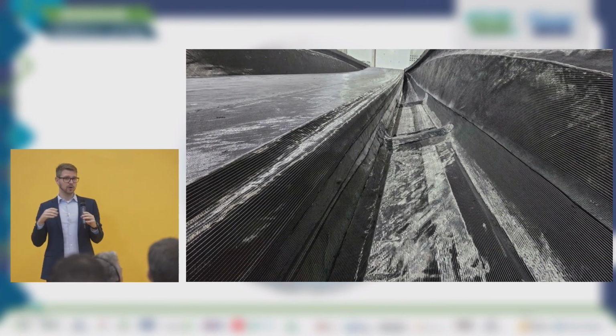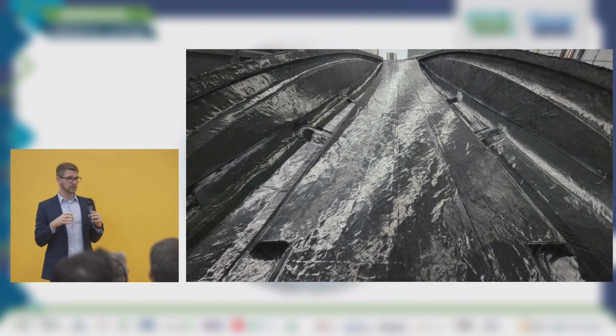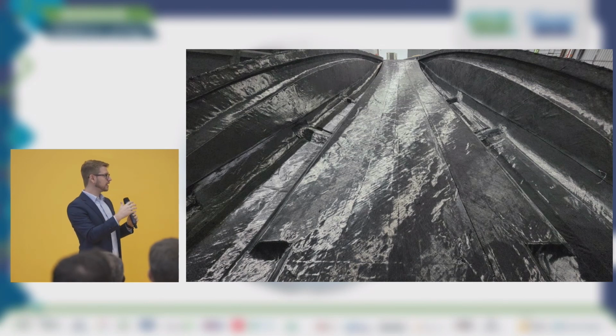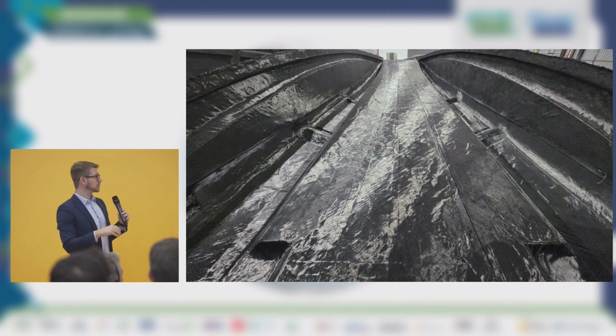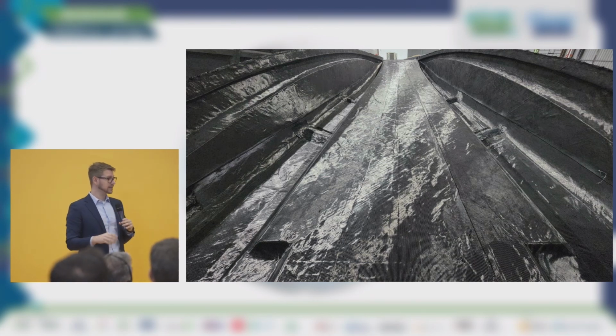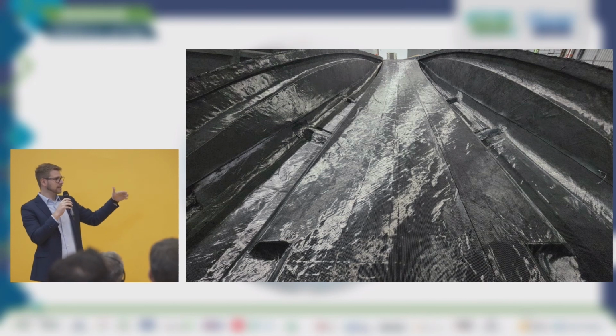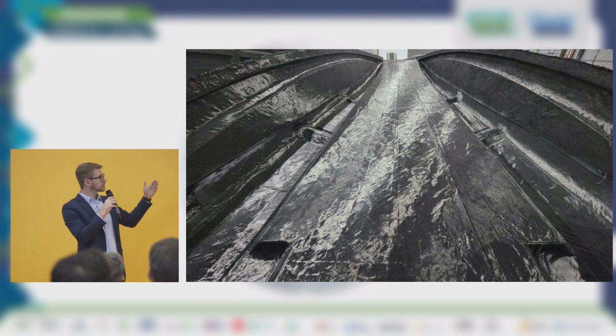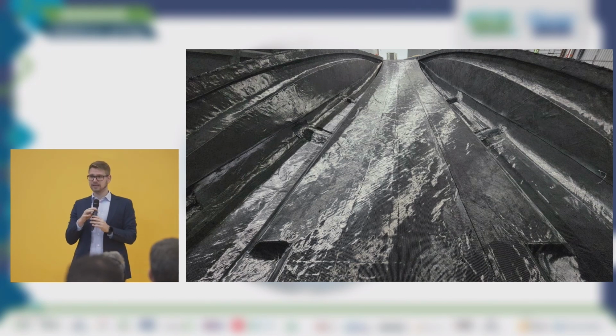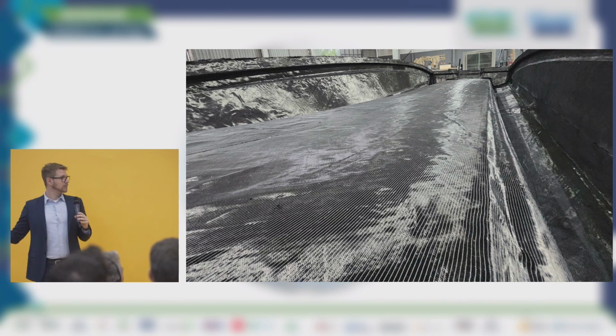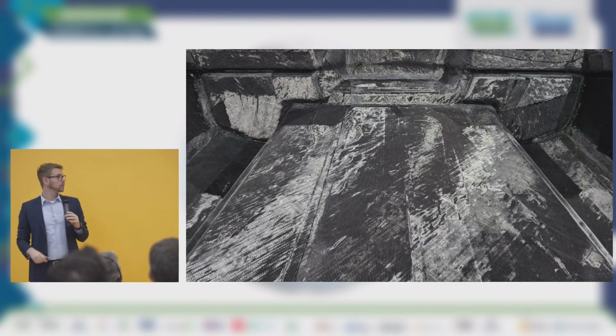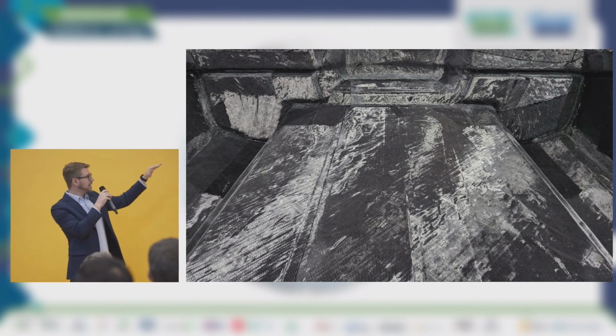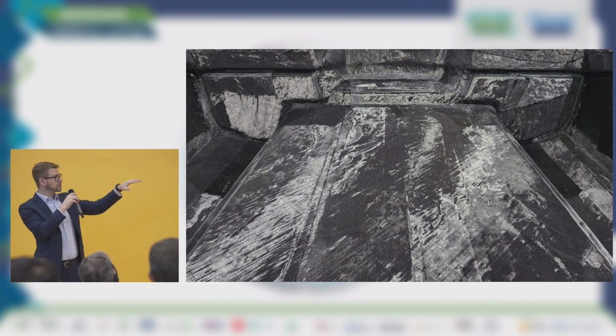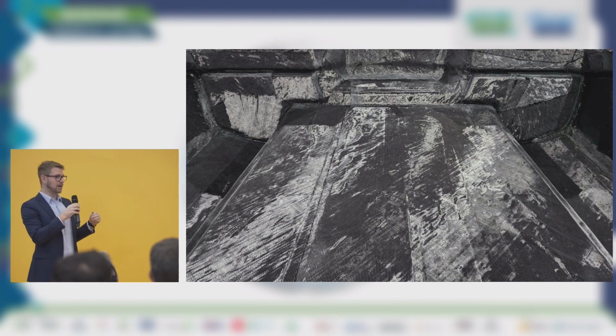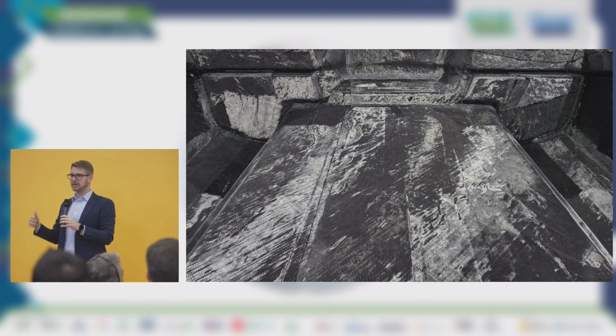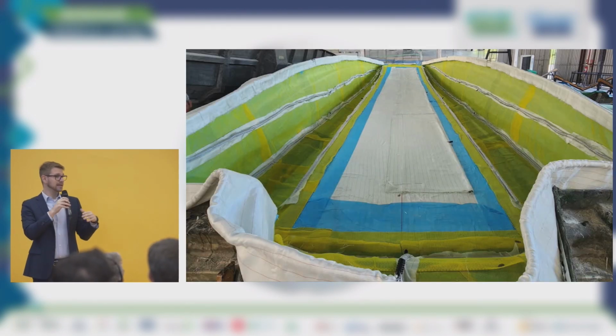All this material has to be put together carefully for the infusion to happen efficiently. This last layer is a 400 grams biaxial. This is a hybrid laminate. We have a mix between biaxial and unidirectional between the layers. One more picture from this part of the boat. You can see the foams. You can see that the laminate is very well compacted. It's very well put, assembled. This is very important for this type of application.